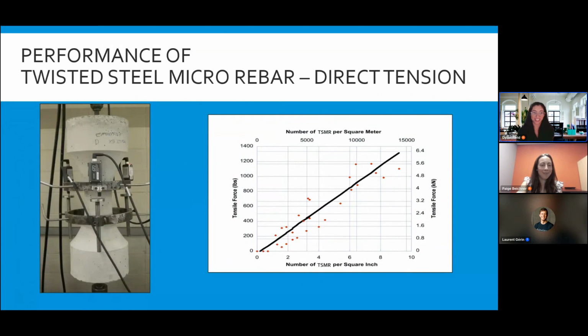This is the dog bone test. Okay, so this is where we take certain dosages of the fiber and we mix it into the specimen you see on the left, and then those two anchors, the one in the top and the one in the bottom, pull to separate that specimen and see when it cracks. And as the number of fibers per square inch increases, so does that force required to crack the concrete specimen.